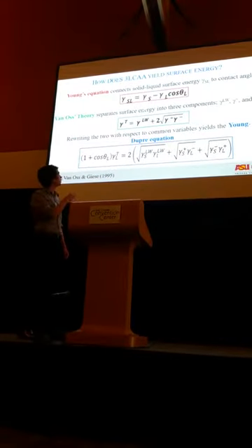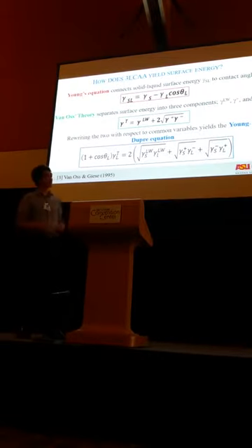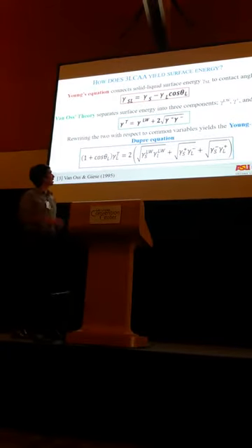Young's equation, described here in this red box, allows us to connect our measured surface angle, or contact angle, to the surface energy of the material. Van Oss's theory, with a mathematical representation shown here in the green box, allows us to further split the surface energy into three distinct energy components.